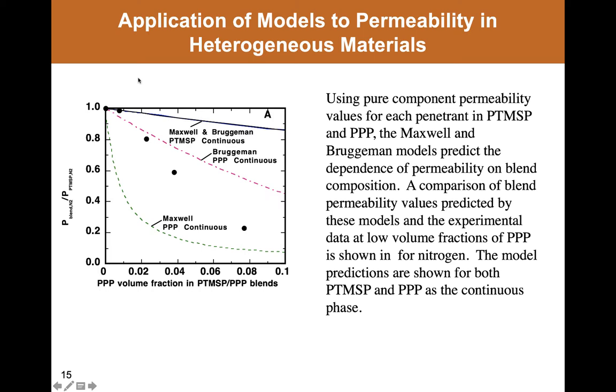And what's being plotted here is the permeability of nitrogen, for example, in the blend relative to its permeability in PTMSP. That's the more permeable polymer in this pair of PTMSP and polyphenyl propyne. And the volume fraction of polyphenyl propyne is starting at zero and going up to about 10% in this case. So at zero volume fraction polyphenyl propyne, this means that this is permeation properties of pure PTMSP with no polyphenyl propyne in it. Permeabilities are normalized to that.